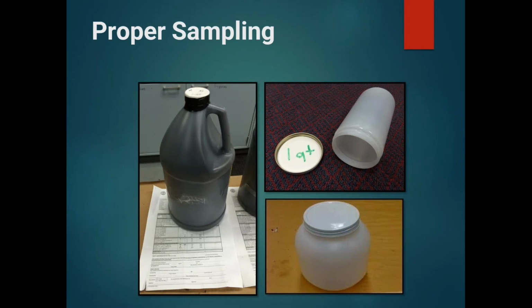So this is a picture of an example of some containers we do like to see used for sampling emulsions. You have just a typical gallon jug container. The reason the wide mouth is preferred is because when that gets into the lab, it's a lot easier to take that lid off and actually stir the emulsion itself and make sure that it's completely homogeneous. It's a little bit harder to get a small opening stirred up well.